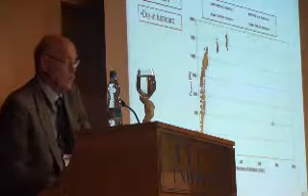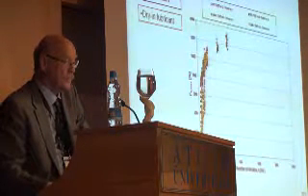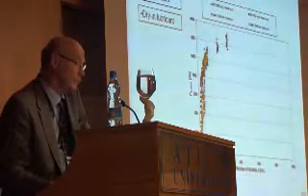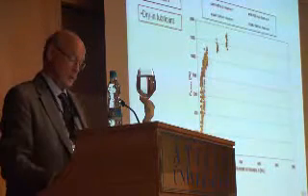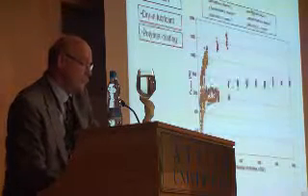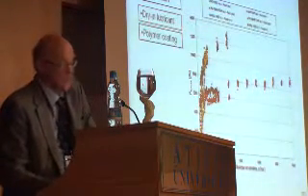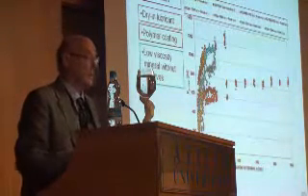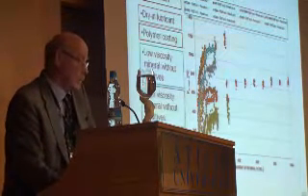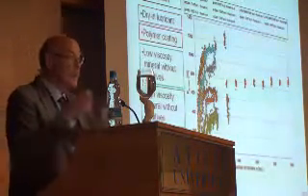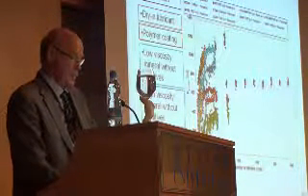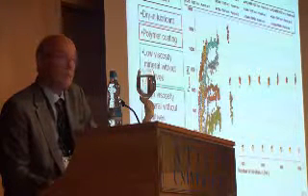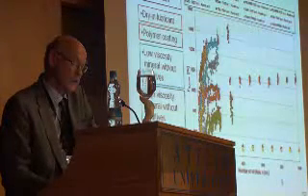Testing different lubricants, like no lubricant, the maximum backstroke force increases heavily with the number of strokes, and so it does with dry-in lubricants, since the lubricant cannot get access to the punch stem. A polymer coating is also a poor lubricant, giving high backstroke force. Low viscosity oil doesn't work at all. A high viscosity oil works somewhat because it adheres to the punch surface, but not very well. Whereas the chlorinated paraffin oil works beautifully. So we can clearly distinguish the different oils.